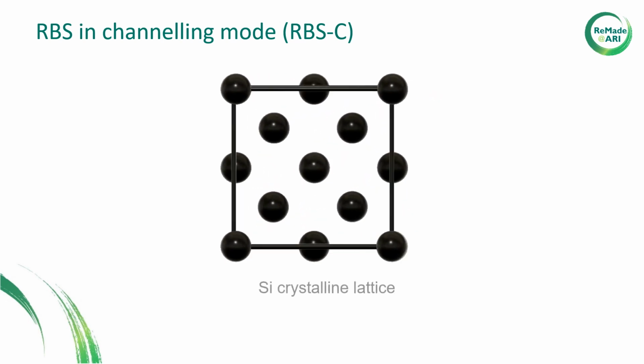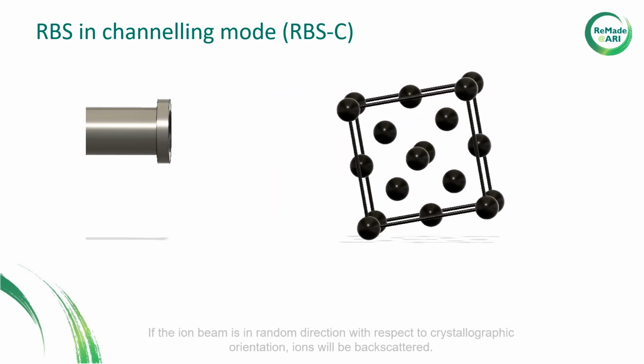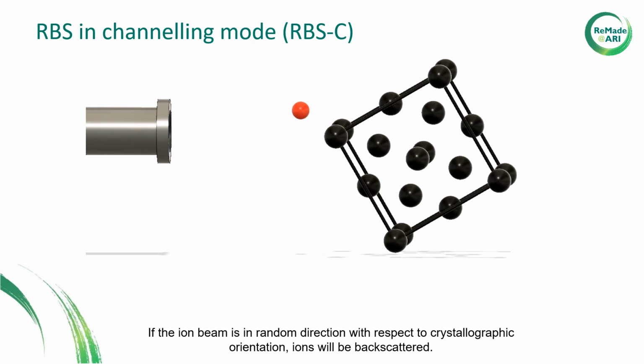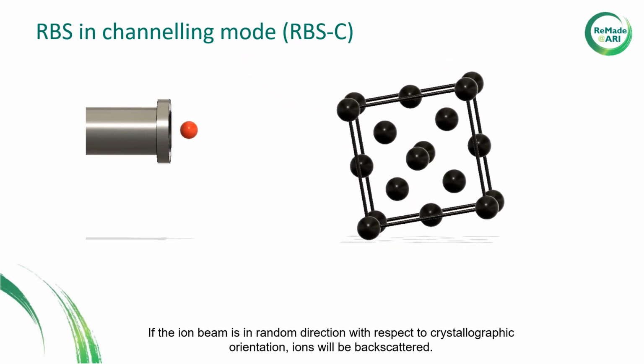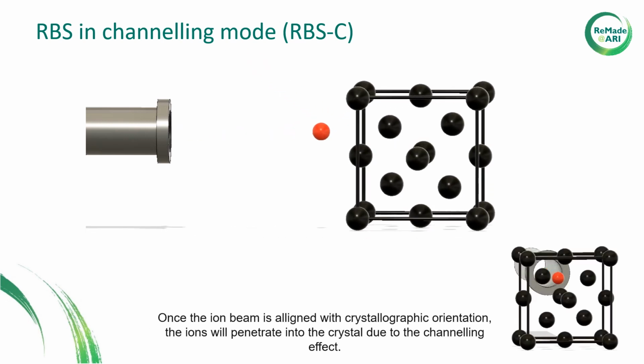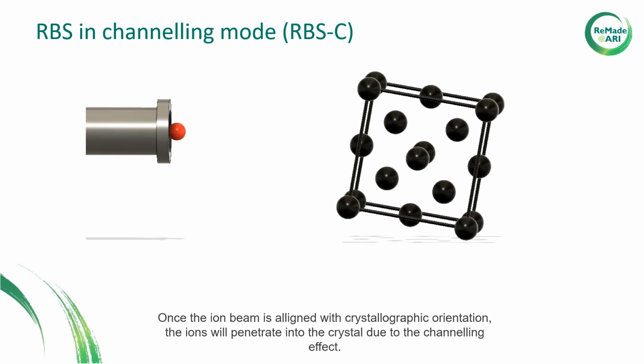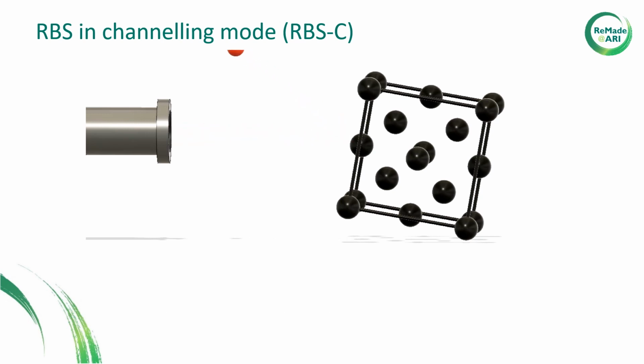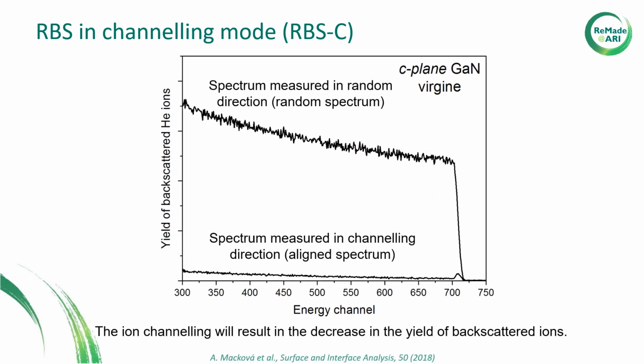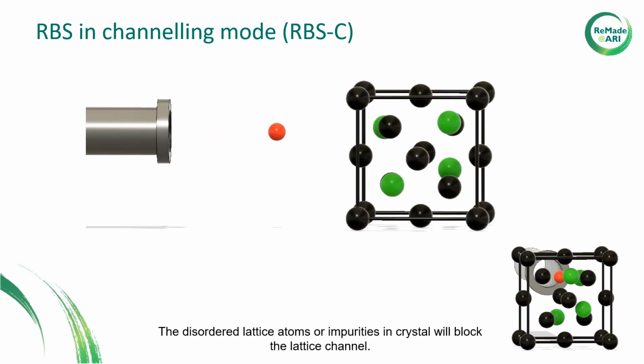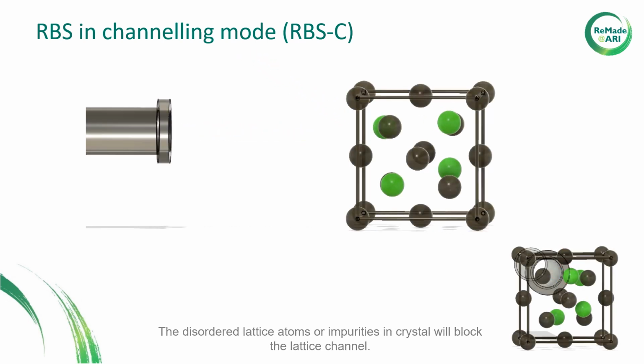The RBS in channeling mode is specifically applied for single crystal analysis, where the lattice atoms form long-range channels. During measurement, the crystal is tilted with respect to the incident ion beam. If the ions bombard the crystal in a random direction, they will be backscattered towards the detector. Once the chosen crystallographic orientation is aligned with the ion beam, the ions will penetrate the crystal and we will observe a strong reduction of yield in backscattered ions, especially in the case of perfect crystals. When the crystal is damaged or has some impurities, the disordered atoms or impurities can block the lattice channel and cause an increase in backscattered yield in aligned channeling spectra.